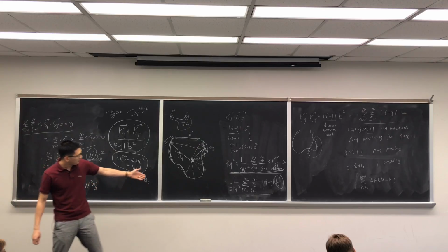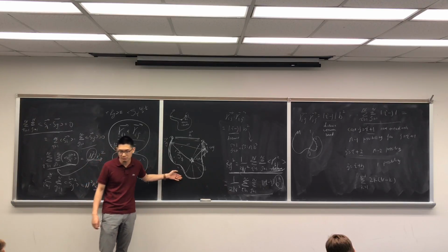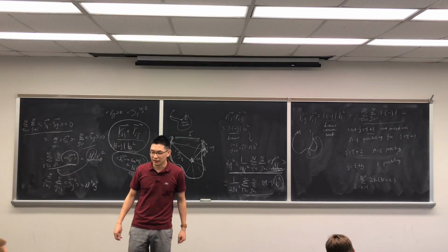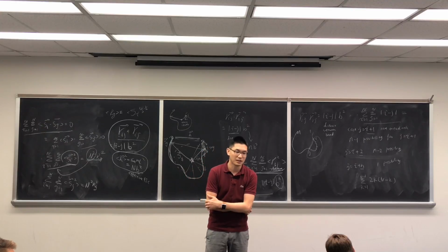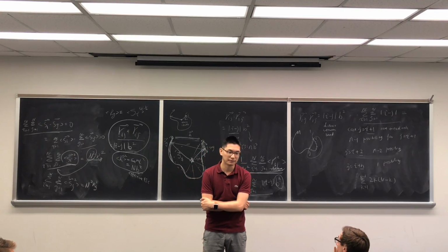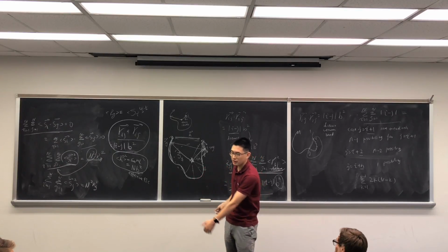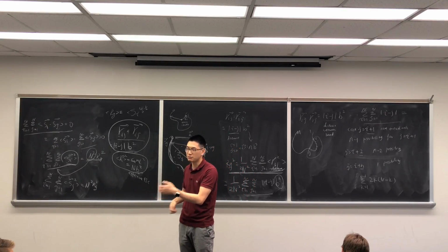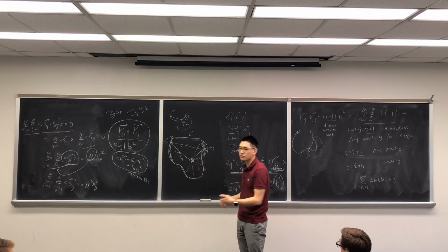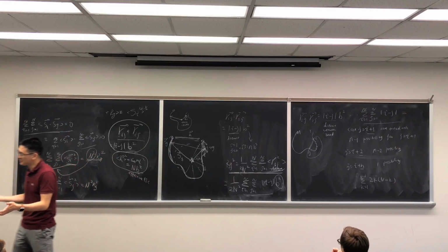And again, if you look back, what we want to do is to explain why Rg is linked to end-to-end distance and how they mathematically relate to each other. In the end, it's a very simple equation I explained to you at the beginning of class. Rg squared is just the end-to-end distance squared divided by 6. And the rest of the class, the last 30 minutes, I'm trying to explain why their math magically works out.